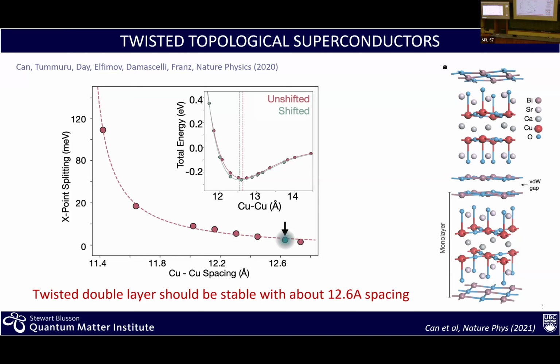So your point is simply you want to rotate without changing the distance between the layers. Ideally, yes, but there's something else going on though. You're changing the hopping path, right? So the hopping path is now changing between the two layers. And so the question is not so much this one, this is fine. The question is, what happens to the interlayer interaction? Which turns out to be a little bit smaller in the undistorted structure, but not remarkably small. So perhaps that would have been a better comparison, instead of showing this one, show what happened to the interlayer interaction.